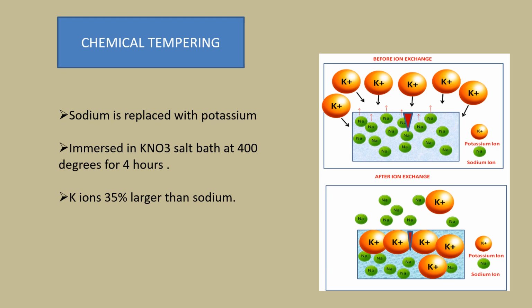Coming to the chemical tempering, this is also called ion exchange. In ion exchange or chemical tempering, the smaller size sodium ions are exchanged with the larger size potassium ions. These potassium ions are 35% larger than the sodium ions, and these larger potassium ions get squeezed in the vacancies which are created by the sodium ion efflux. With this squeezing of the potassium ions, it results in introduction of some amount of stresses into the material. And this can be brought about by placing this in potassium nitrate salt bath at 400 degrees centigrade for 4 hours.